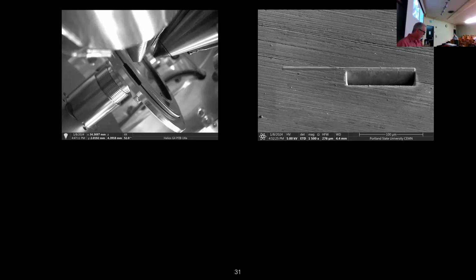I mentioned gas precursor. So I decided I wanted to make a cut in this copper gasket because there's no IP on it. We can see here, if you can see my mouse cursor, there is a protective cap I put down. This is something we couldn't previously do, because this is actually a mixed protective cap. This is a platinum carbon mix, which is a little bit harder, so it holds up to the beam a little bit better.